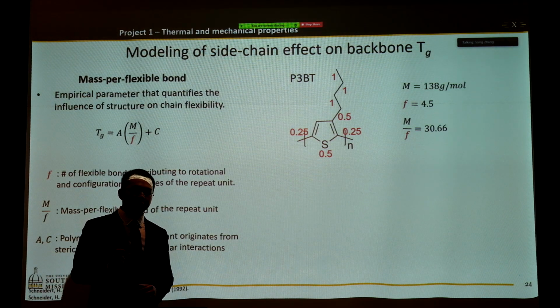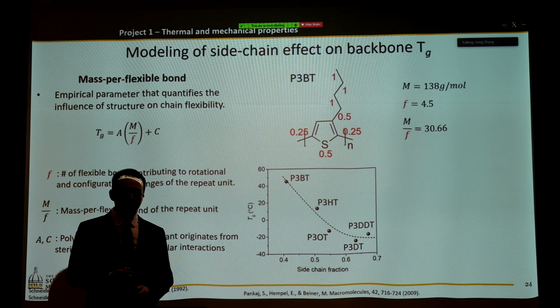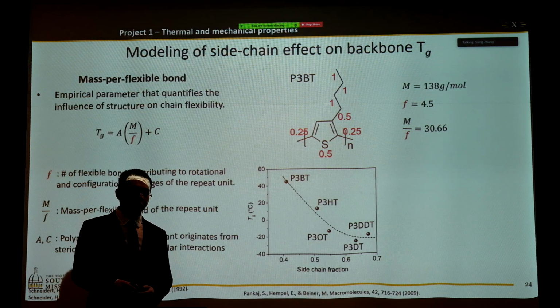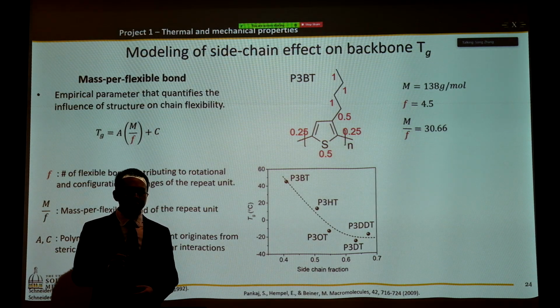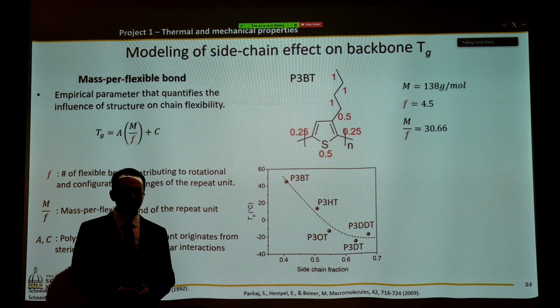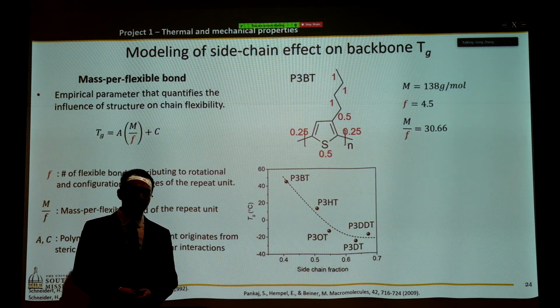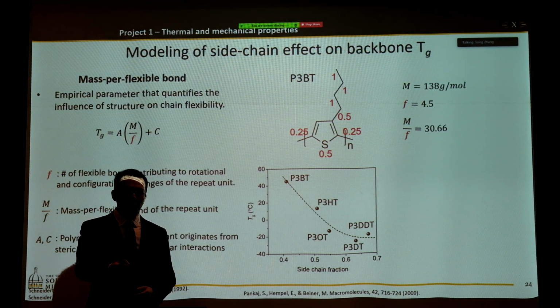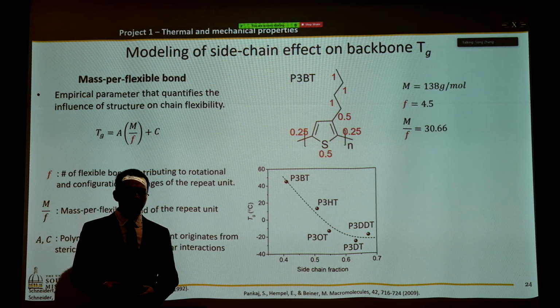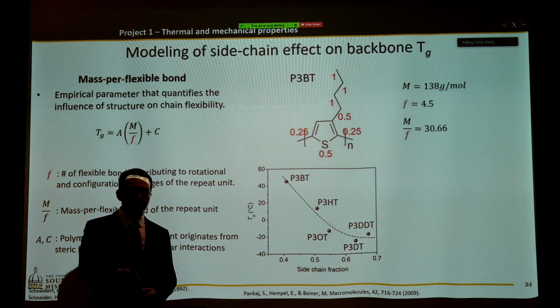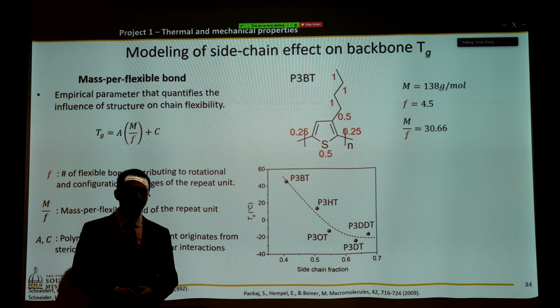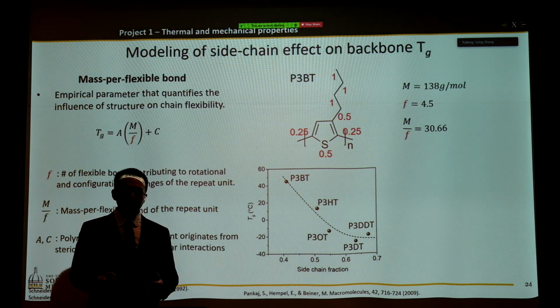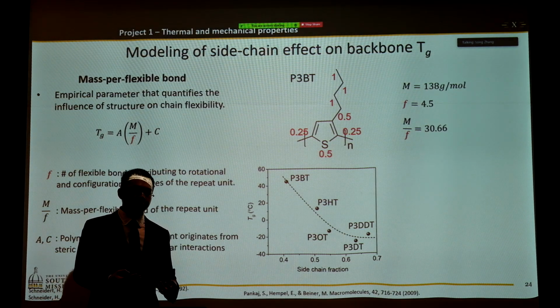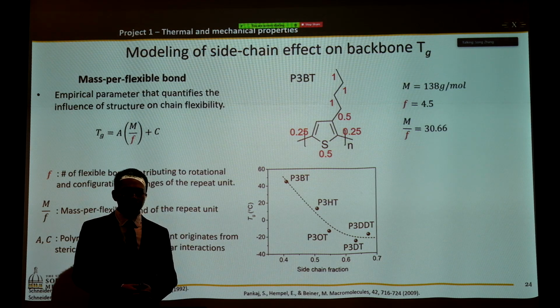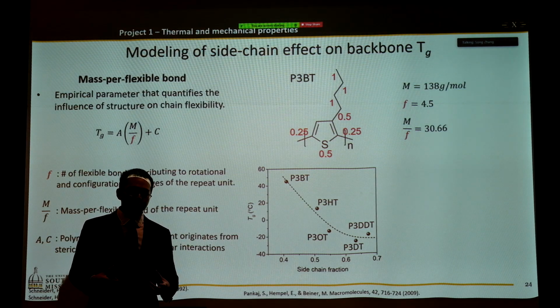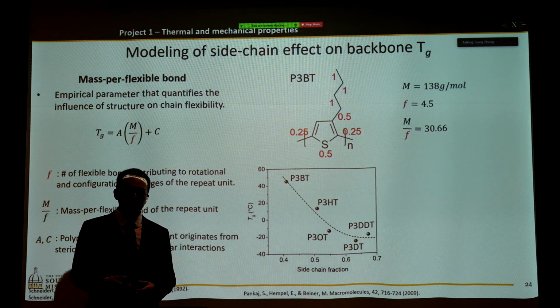However, just using this number is not enough. Let's take a look at the glass transition for a series of side chain engineered P3ATs, with increasing side chain length, from P3BT all the way to P3DDT. And in this curve, the Tg versus side chain fraction curve, we saw that the trend is very similar to the molecular dynamics simulation results, because the side chain is taking up most of the polymer itself.